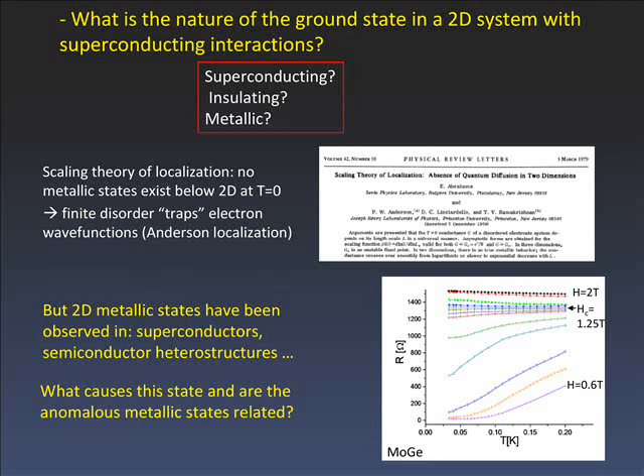Experimentally, for many years there's been evidence of 2D metallic states as the temperature is lowered, and these have really not been well understood — appearing in superconducting systems and semiconducting systems. This is from my own thesis work on 2D metallic states. You can see resistance versus temperature as the temperature is lowered, saturating out into what seems like a finite resistance, which is just not understood theoretically.